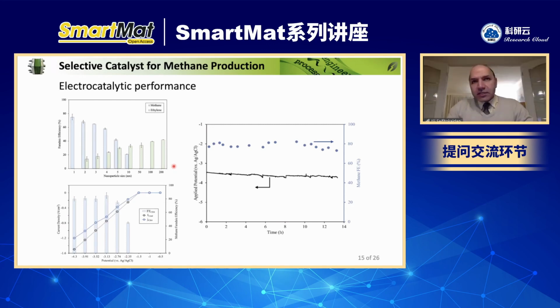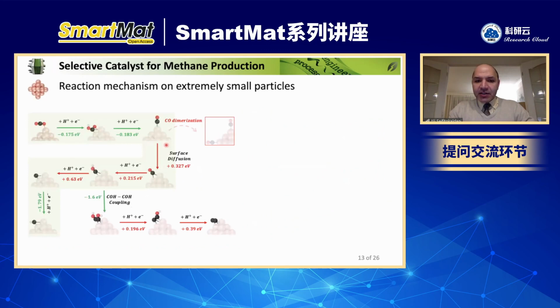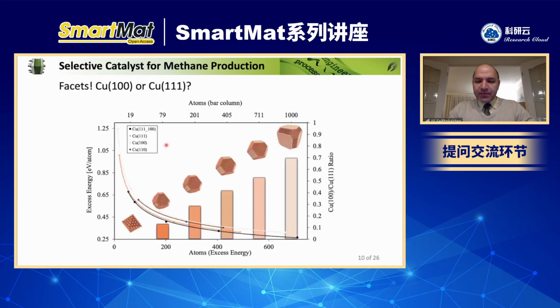Yeah, thank you. This is a very interesting question, and there might be multiple reasons for that. I mean, just being focused on what we did here to justify why larger particles can produce ethylene or the CC coupling is easier, I can refer to this one. As I said, when you increase the particle size, although this is not actually even in the order of 200 nanometer, you can see the 100 facet to 111 ratio increases. So you have more 100 facet.